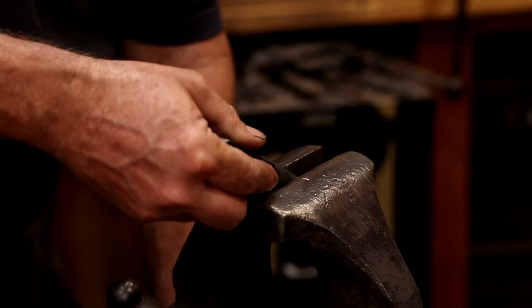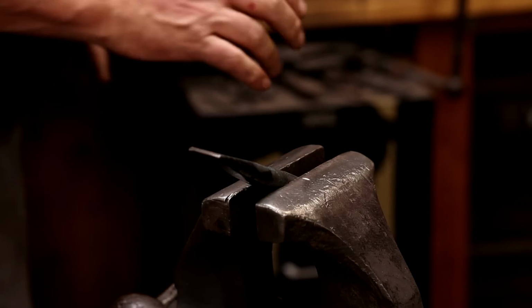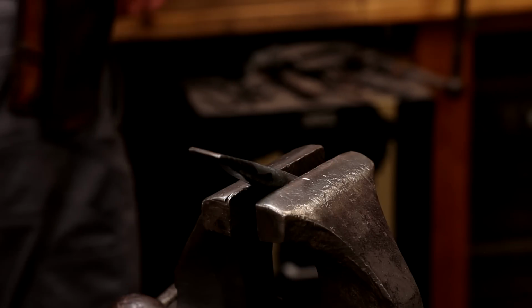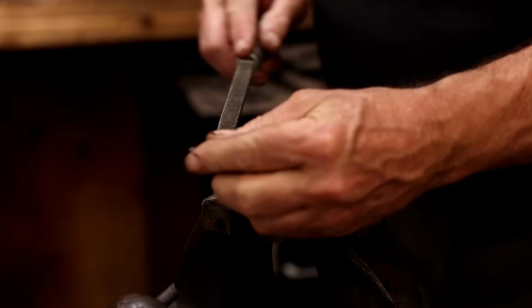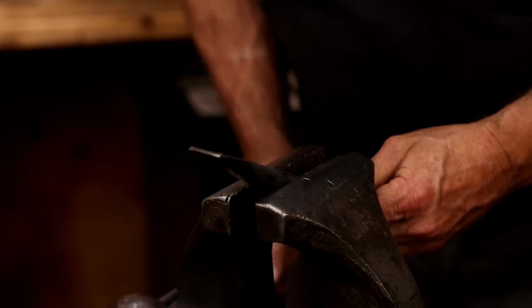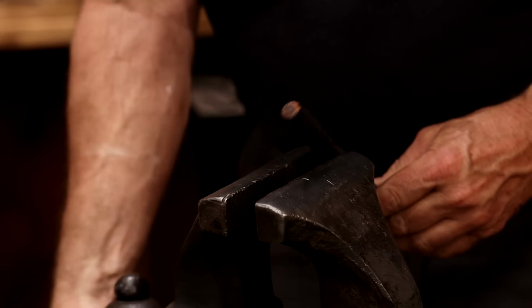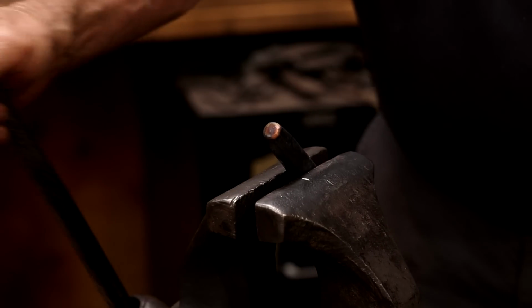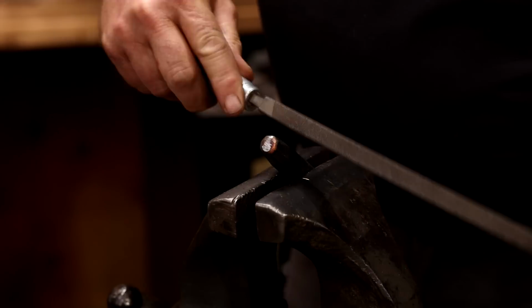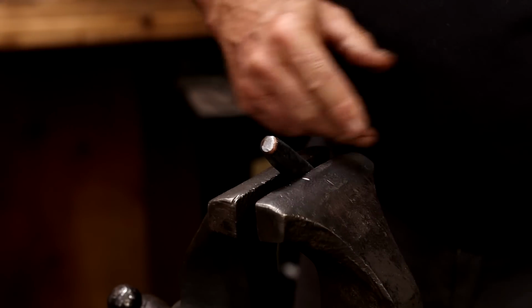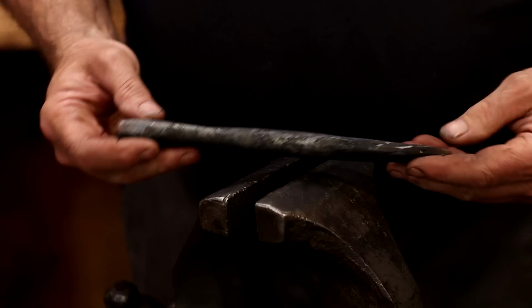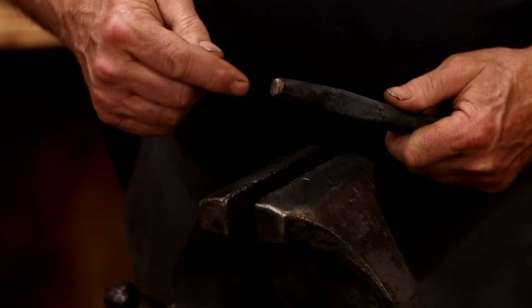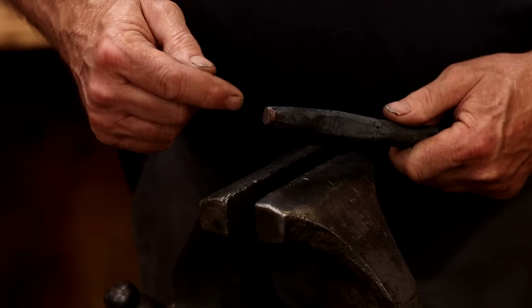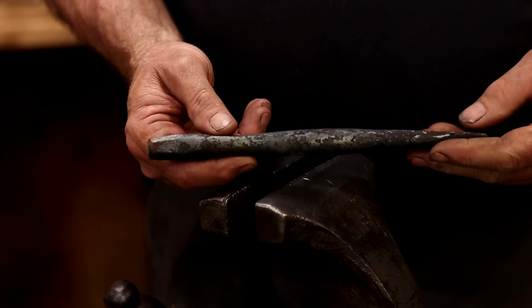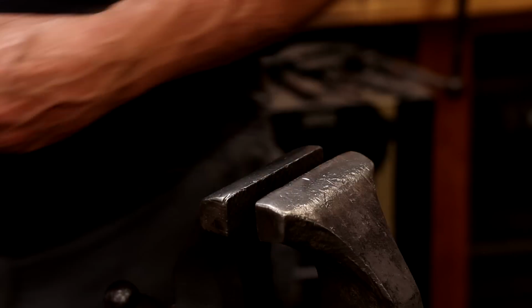Go ahead and test this chisel and see how hard it got, and then also test the struck end and see if it's softer than the cutting end. It's good and hard on the cutting edge. Not hard at all on the struck end. So that should not hurt our hammer at all. If it mushrooms too much, that means I should have hardened it more, and that's just something we'll test as we put these to use.